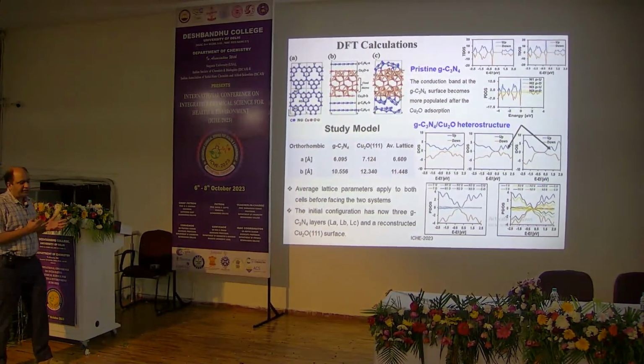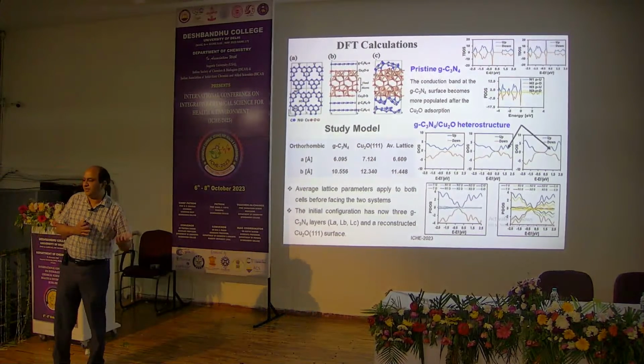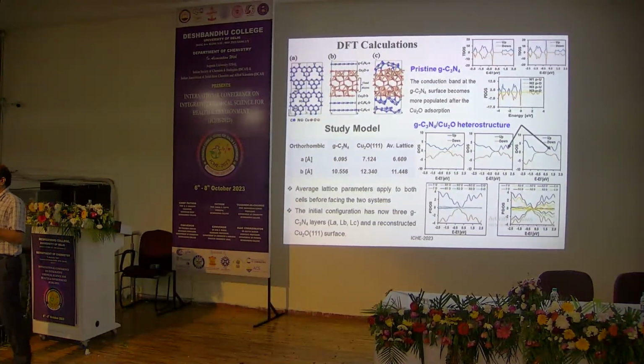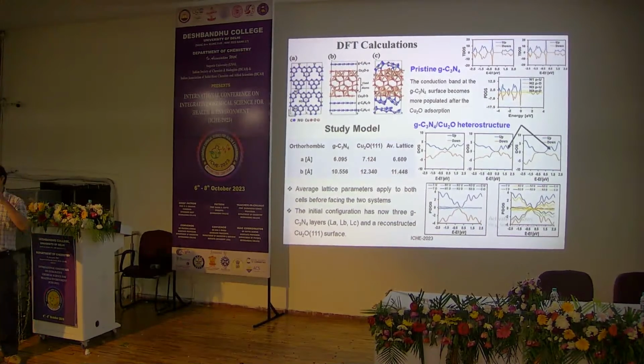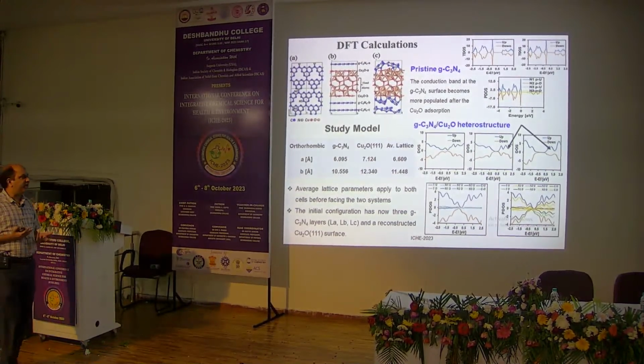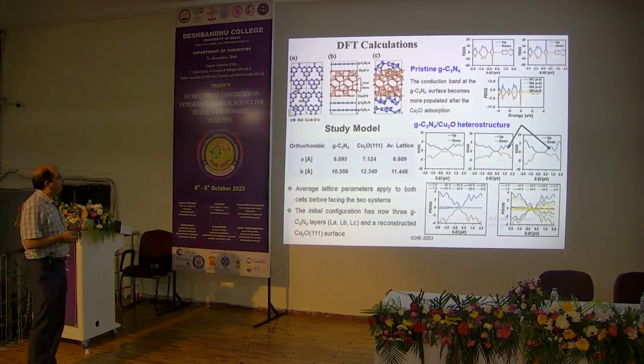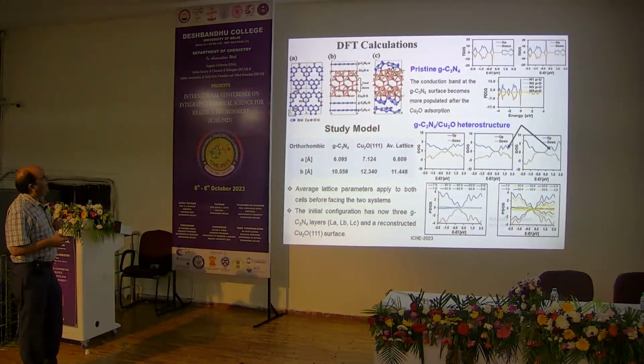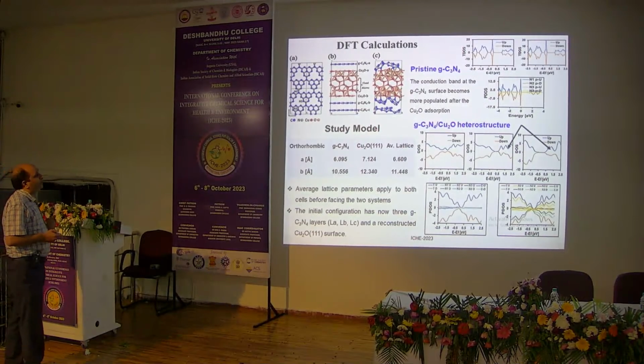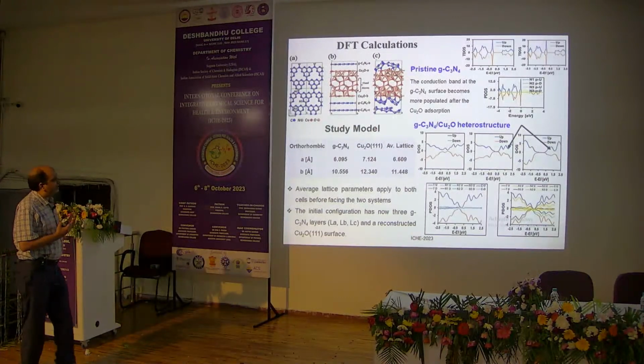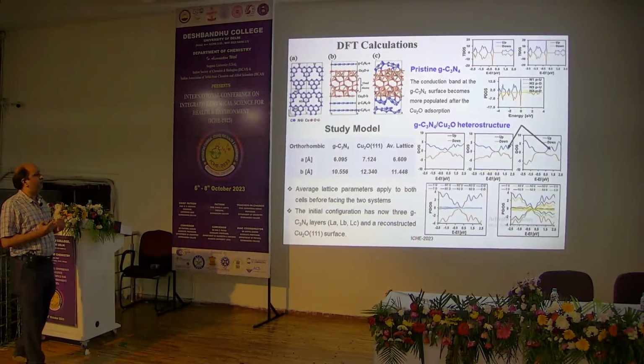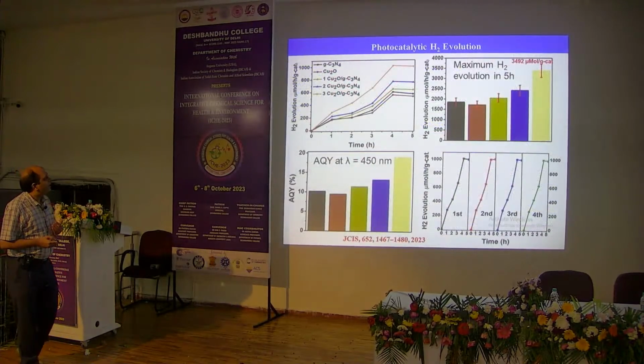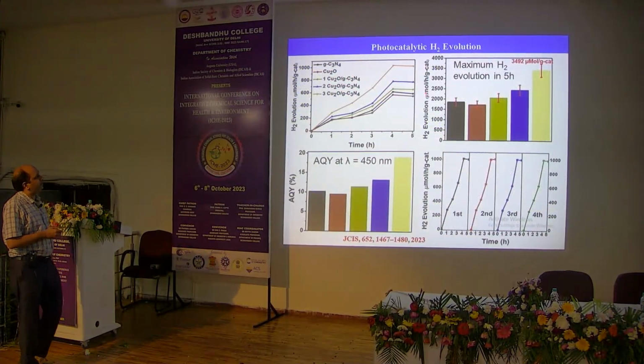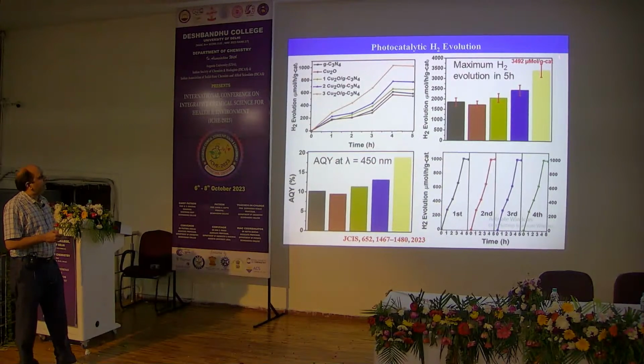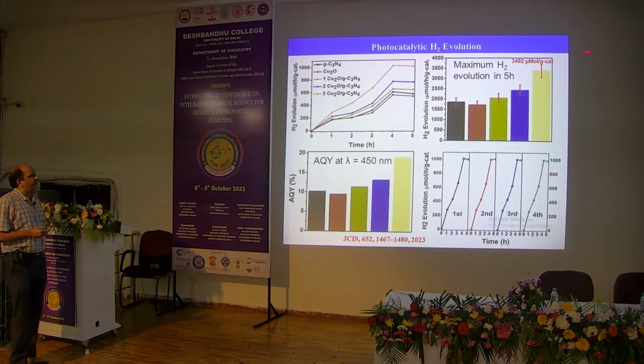Here, if you see the structural information of graphitic carbon nitride and copper oxide, they have different structures. So first we produce the structural similarity, so that when we do this study, the model shows that during the formation of the heterostructures, the conduction band becomes more populated, which is helpful for our study. Here, if you see the detailed investigation of hydrogen evolution, you can see the 30% loading of the copper oxide over graphitic carbon nitride can produce